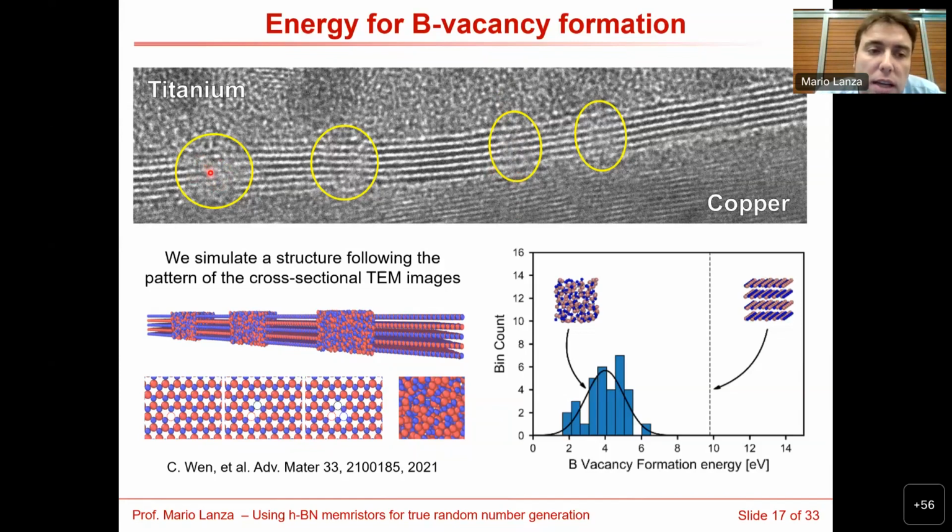In a TEM image, the atoms are black, and the bright signals are the spaces between the atoms that arrive at the electron detector. So here, what we are seeing is gray color everywhere, okay? Which means that these bright places are not bright anymore. There are atoms there. So we have atoms that are not where they should be.